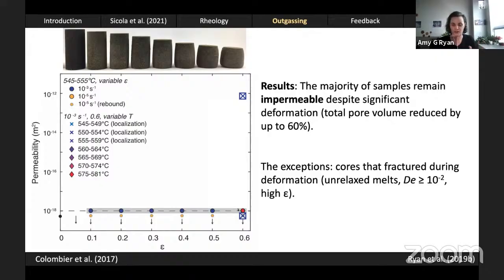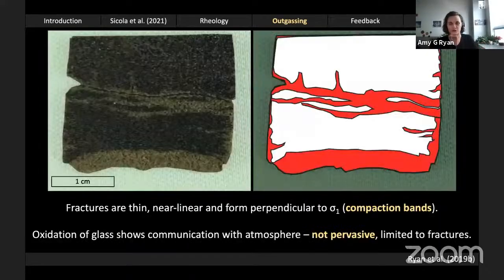I want to show you what those fractures look like now. As I said earlier, foam glass oxidizes when the melt encounters atmosphere at high temperature. So what we can do is take one of these fractured samples, cut it open, and retroactively see where the fractures formed. I've got an image here of one of my deformed cores, and then a cartoon on the right showing the same features, but just a little bit more clearly.